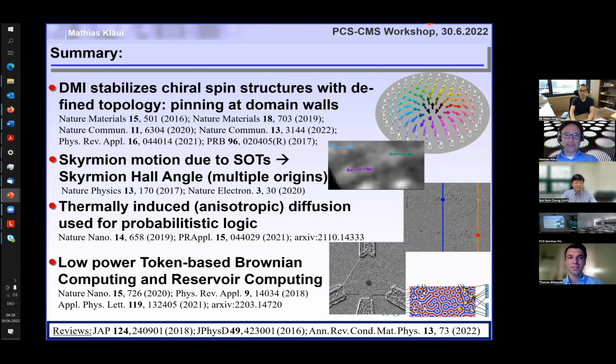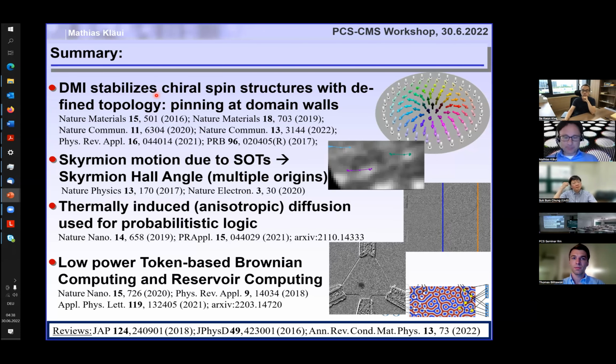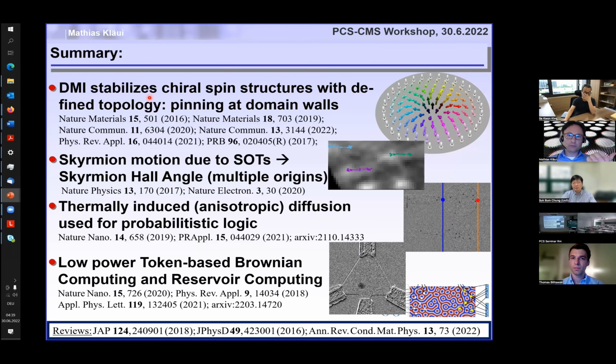You mentioned in your initial slides that there is data showing the calculation of the Dzyaloshinskii-Moriya interaction strength and the one measured in experiment. How do you measure it experimentally? This strength of Dzyaloshinskii-Moriya interaction? There are different ways. So one is you can measure the asymmetric spin wave dispersion relation because spin waves moving left and right will have different energy for the same k vector.